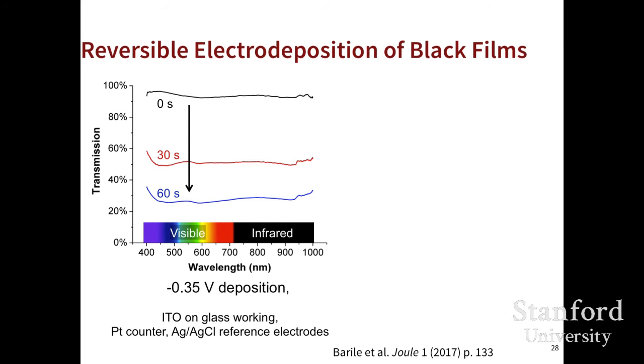This next slide shows the spectrum. You've already seen pictures, so you can see that these things do look black. And here's just quantitative data showing how the spectrum is going down with time. It also shows that this just keeps going into the infrared, and I'm not showing it here, but the attenuation goes out well past 2,000 nanometers, which is as far as we've measured it. And of course that makes complete sense. This is metal, and metal is very effective at blocking light over an extremely wide spectral range.